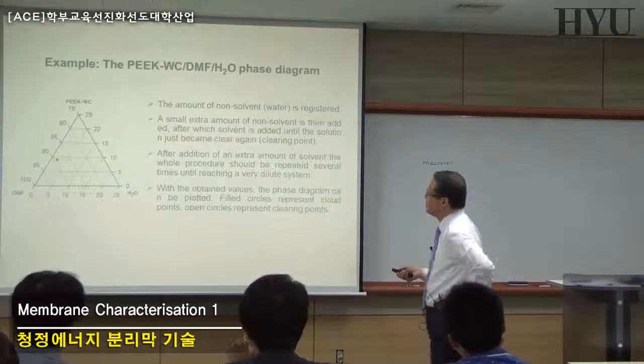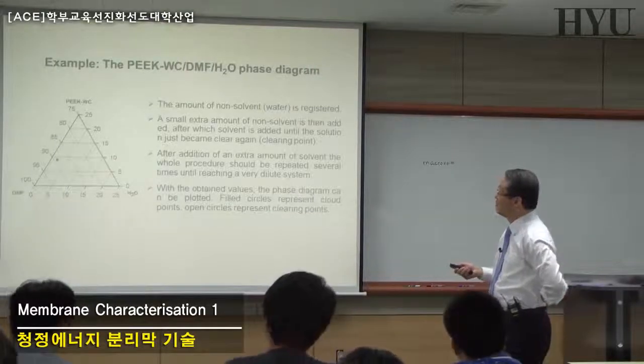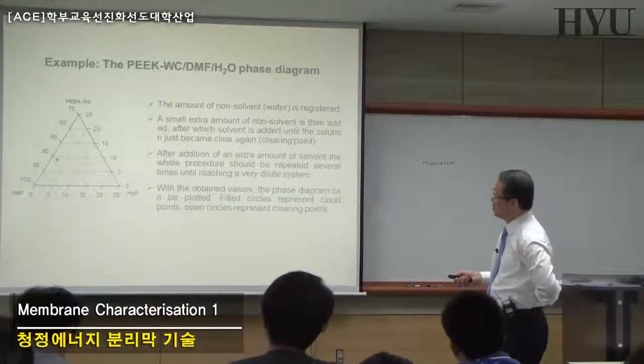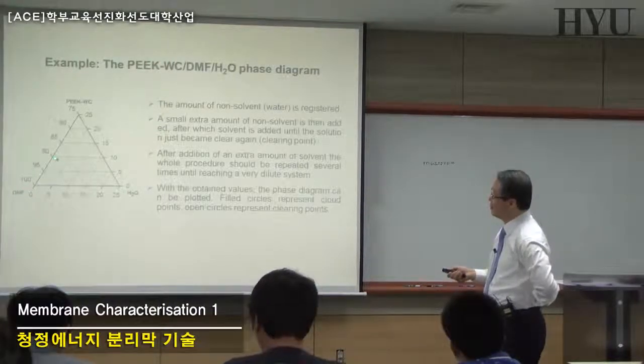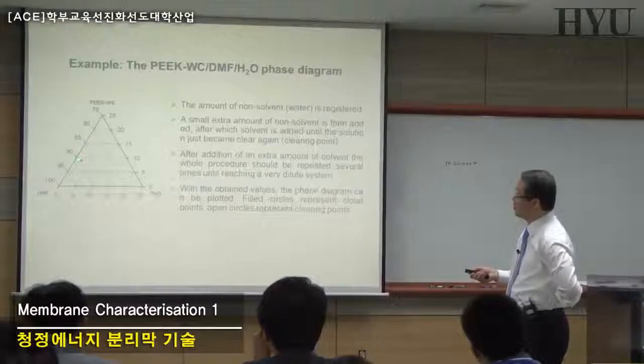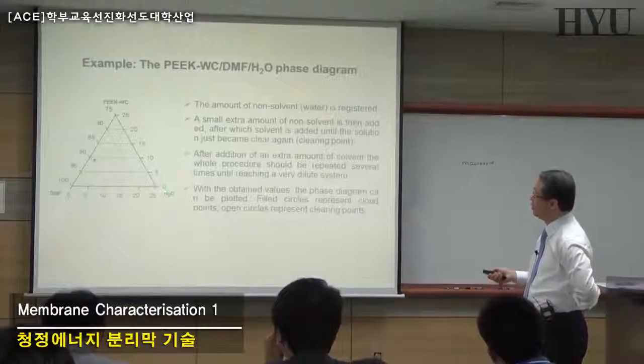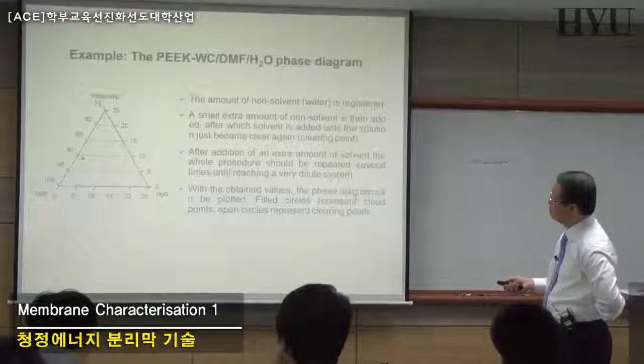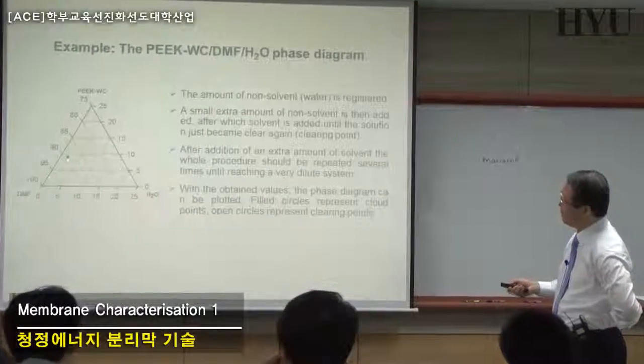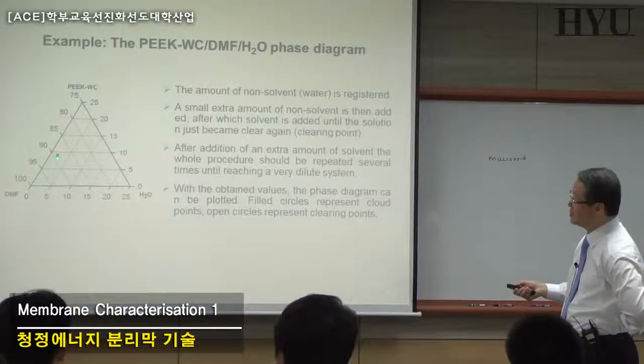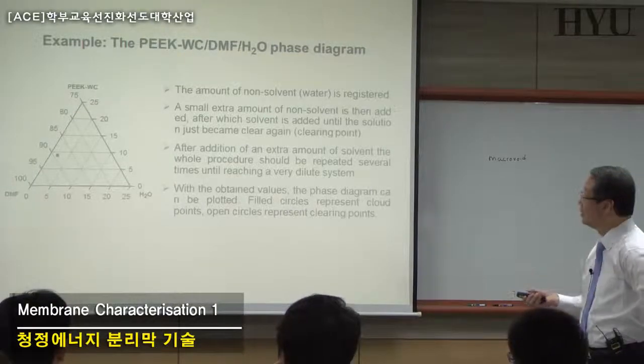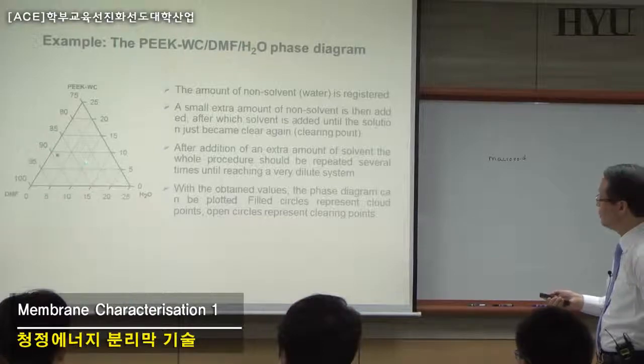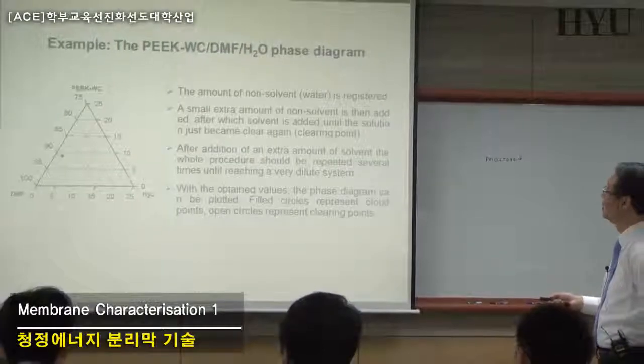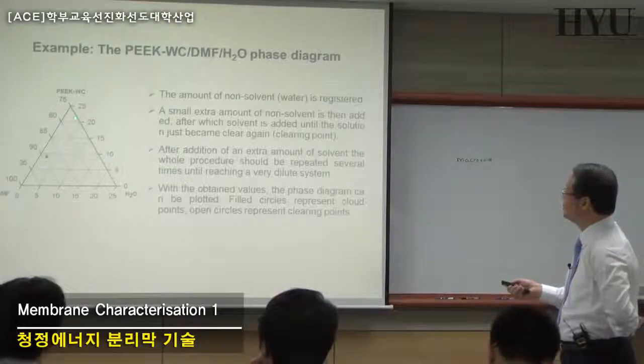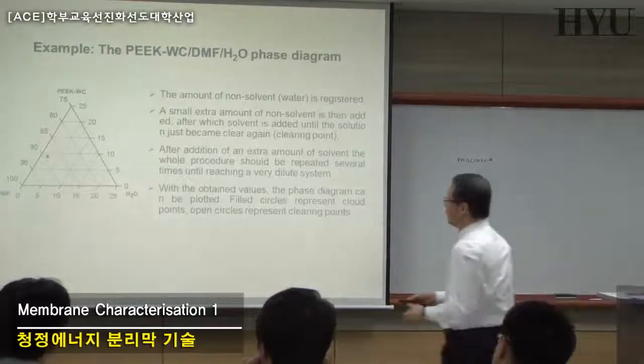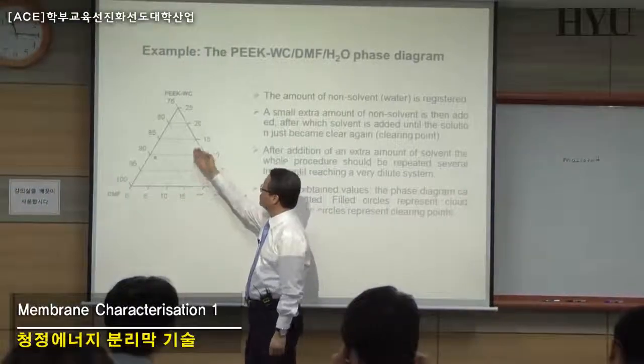So for example, this is an example of some polymer and some solvent like DMF and water, and you start from this point. This point means that you have a small amount of water, maybe 1% or 2% of water in your dope solution. The polymer content might be, let me see. So this is the water content.